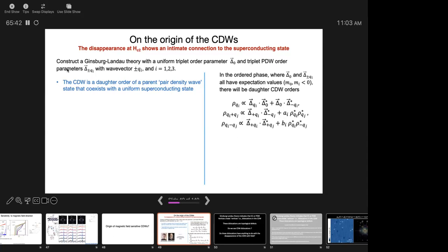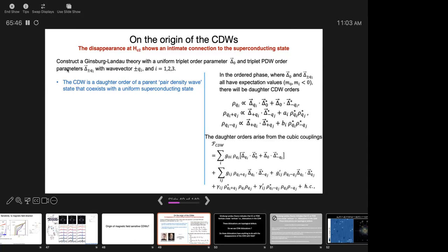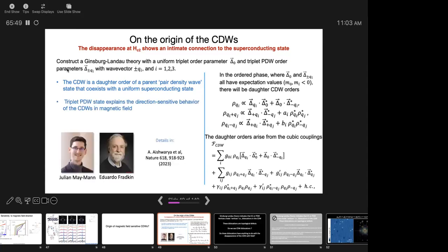This CDW will have the same wavelength as your pair density wave, and of course double it as well. And this PDW state explains the direction-sensitive behavior of the CDW in magnetic field. Okay, so this is a hand-waving explanation. To get the CDW, you need two ingredients: a homogeneous superconductor and a pair density wave. The combination of these two things gives you the charge density wave. If you kill homogeneous superconductivity, you will also kill the CDW in this scenario. Or if you kill the pair density wave, you might kill the charge density wave. So that is the scenario.